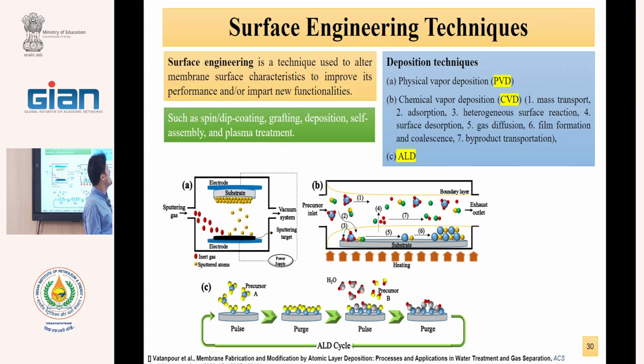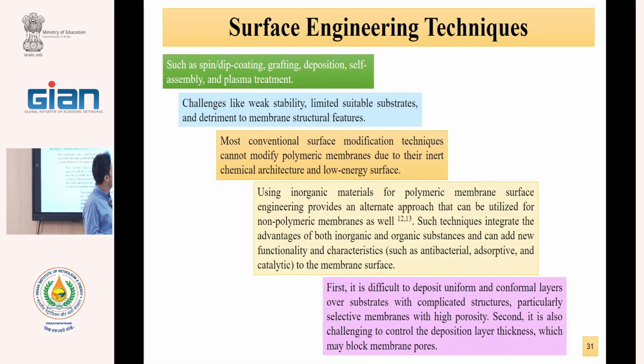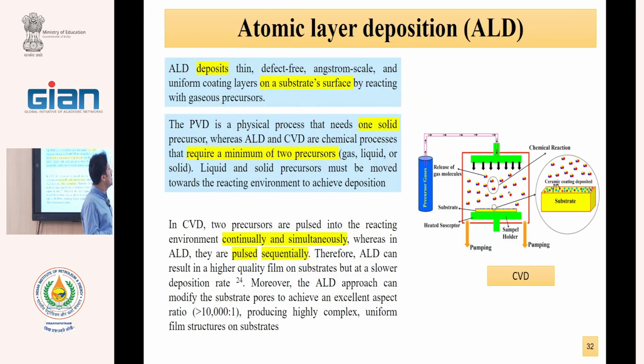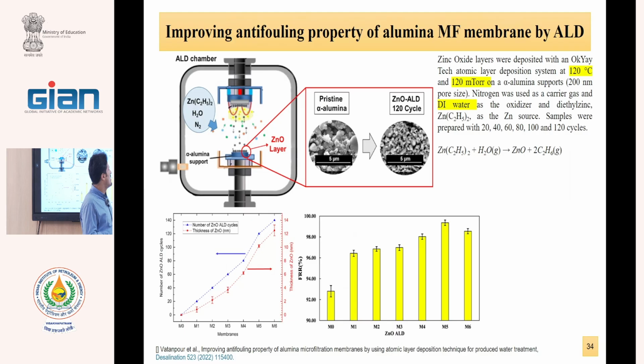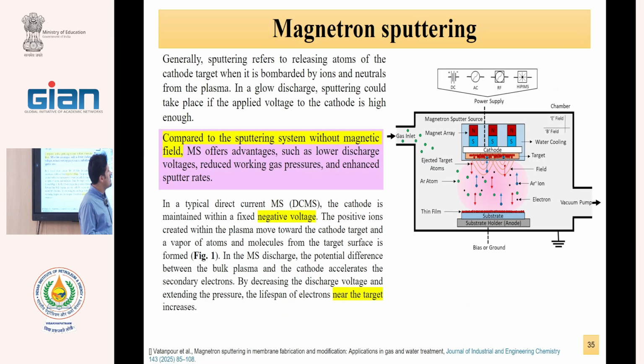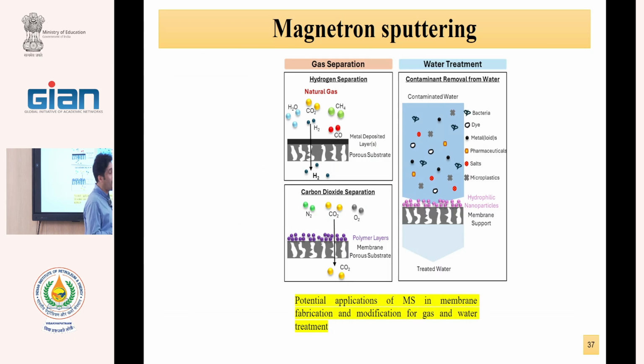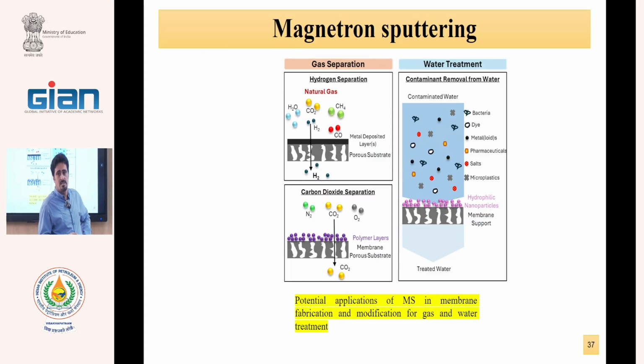And we can produce very, very good membranes with ALD, atomic layer, chemical vapor, or with magnetron sputtering. We can fabricate very good membranes. But the sputtering device is very, very expensive and mostly used for membranes at electronic chip scale and as membranes in sensors. In sensors, we have a very small surface, and we can produce the membrane layer on a very, very small scale for separation of one component from another, and then detect with a sensor detector.